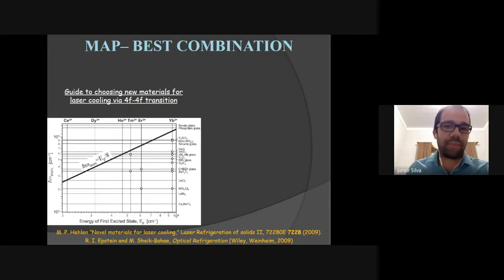Dr. Markus Hehlen made this map, and we can see here, for example, there is this straight black line. Here we can see in the y-axis maximum phonon energy, and in the horizontal axis energy of the first excited state. Okay, so our material needs to be below this straight black line. We can see above the ions here, ytterbium, erbium, thulium, holmium, and so on. And here we can see the families of materials. For example, the oxide family presents higher maximum phonon energies, and after that, going down, fluoride, chloride, and so on. So we need to put our material here to observe cooling.